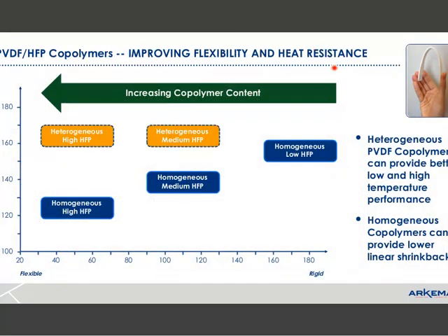Okay. This is a very useful slide for trying to understand the different grades and ranges of PVDF HFP copolymers. What we have is melting point. What's missing here is a description down below, and that should be flexural modulus, which is in kPSI. Looking at the bottom axis, on the far right are rigid materials, and on the far left are flexible materials. Coming up to this green arrow, as we increase our copolymer content, we produce softer and softer products. The first type of product I want to talk about is homogeneous PVDF HFP copolymers. With homogeneous products, where the copolymer is uniformly distributed, as the amount of HFP increases, the product gets softer, but the melting point also becomes depressed.